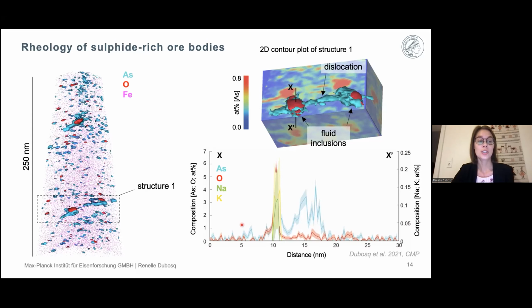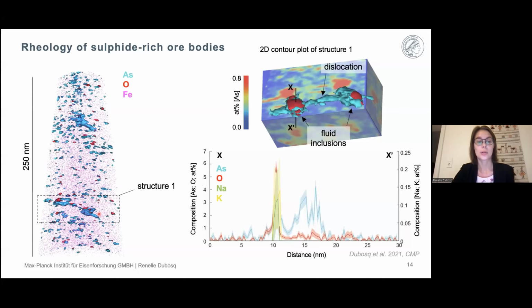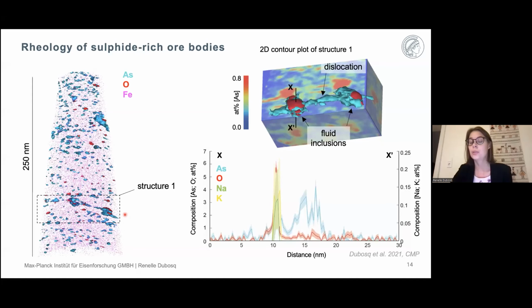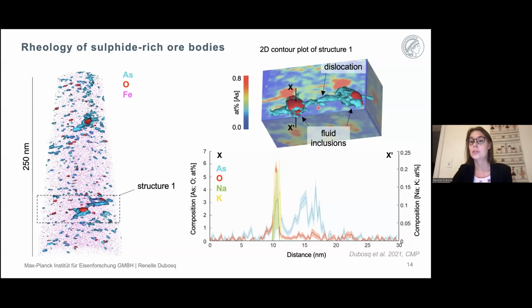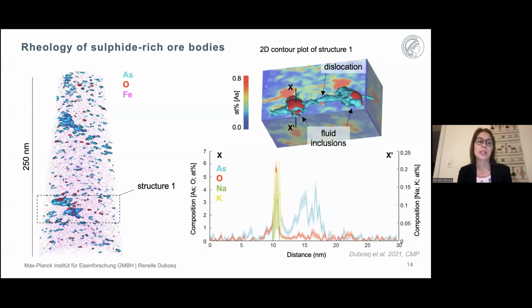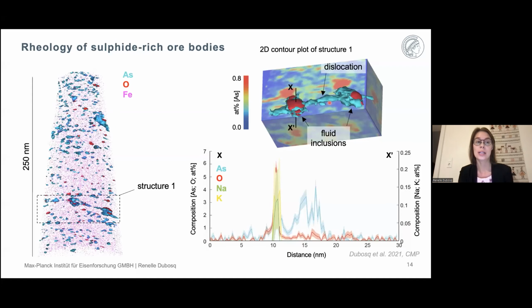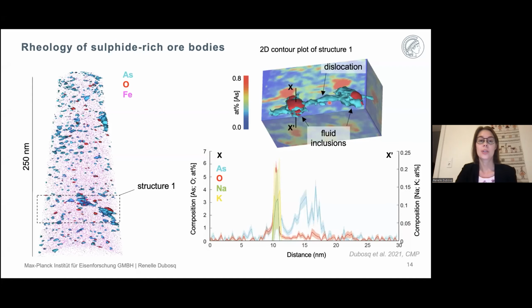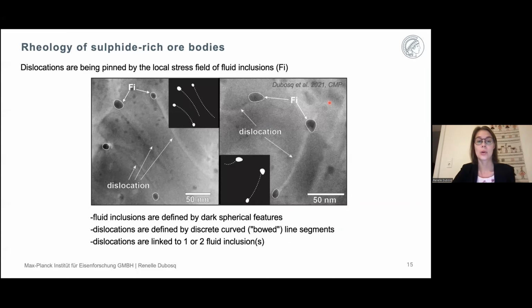So if we look at these larger fluid inclusions here, for example, in the box here showing structure 1, we notice that these larger fluid inclusions appear to be linked together by arsenic-enriched linear features or arsenic-enriched dislocations. So to confirm this configuration, I also wanted to look at a similarly strained region in an adjacent crystal with STEM analysis. So here are the STEM images, and we can see in these images that we have fluid inclusions everywhere. So these are these darker spherical features. And we also have dislocations in the form of these curved or bowed line segments. And what we notice once again is that each of the large fluid inclusions appear to be linked to dislocations, either 1 or 2 dislocations.